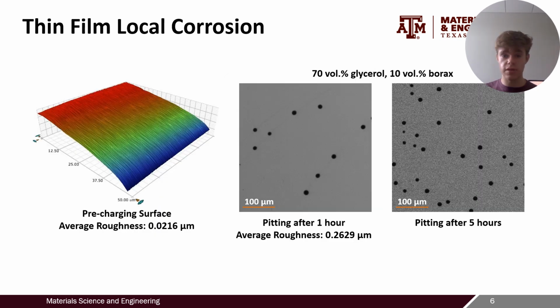So pitting was actually confirmed by comparing surface roughness before and after charging, and after only 1 hour charging in a 70 volume percent glycerol-based electrolyte, there was a 10x roughness increase. So that's going from an average roughness of 0.0216 microns to 0.2629 microns, which is actually over a 10x increase. Additionally, we can look qualitatively at the SEM photos on the right to see that pitting dramatically increased with charging time from 1 to 5 hours.